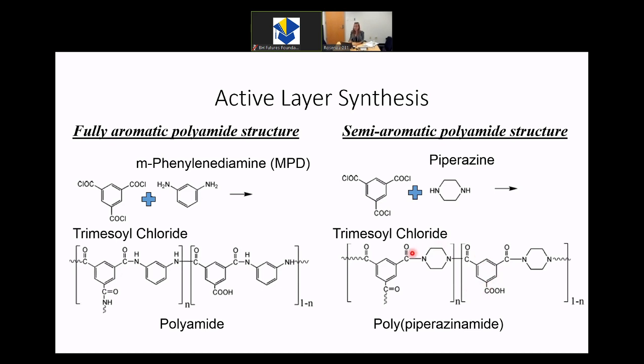When these two respective reactions occur, they produce this polyamide here, and then the semi-aromatic reaction produces a polypiperazinamide that you see here. So not to get bogged down in the chemical structures, but this is the actual structure of the active layer, that yellow top layer of the membrane. So for reverse osmosis membranes, they're typically fully aromatic structures such as this. So it would be this structure.